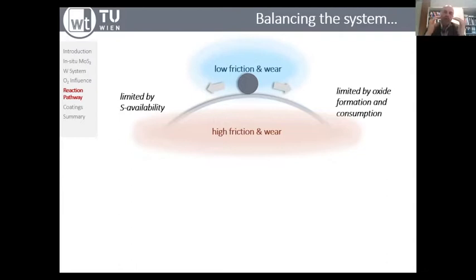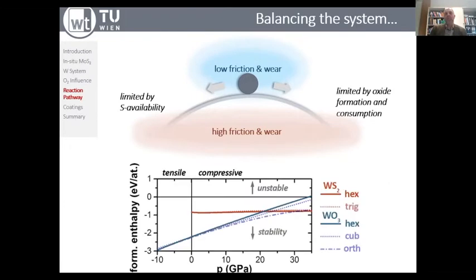So you need to find a very defined balance between sulfur as a delivery source and the oxidation rate of the material as an intermediate approach, to find the optimum parameters so that you can form the molybdenum disulfide and the tungsten disulfide in situ, and then tackle the friction and the wear. So we also try to understand, okay, how does that go hand in hand? Because we know that the tungsten trioxide actually is rather stable. When you start increasing the temperature, of course, the stability goes down.